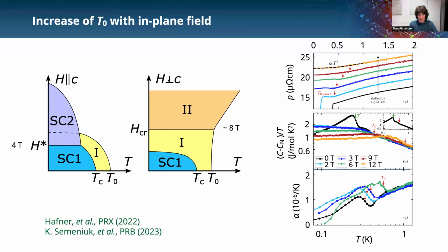When we apply a field in the plane, then this transition temperature remains almost unchanged up to 8 Tesla. Then there's a first-order phase transition to yet another state, and then the transition temperature increases. And here on the right, I don't have time to go through this, but there's data supporting this line here.